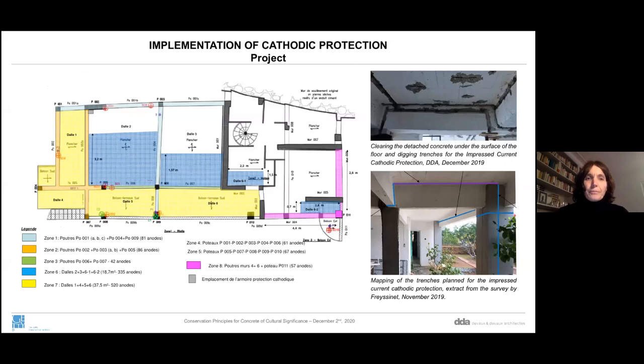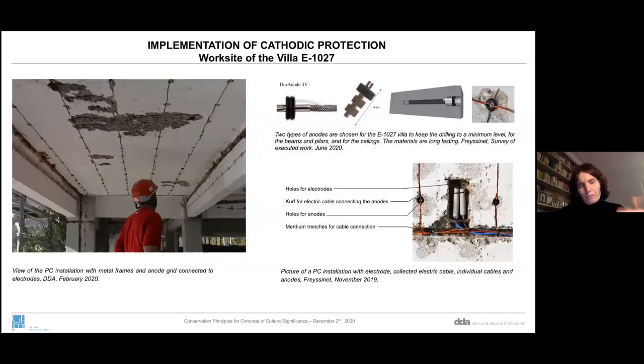Here you see the work which is going on, and you can see the ceiling where we purged the concrete which had fallen down. And then you see the anodes. Normally the anodes are much bigger, but we had a ceiling which was only 7 centimeters, so we had very small anodes of 4 centimeters. You see them every 30 centimeters connected with the cables, and you see the trenches, which put all the steels together to connect them and relay them to the electrical installation.